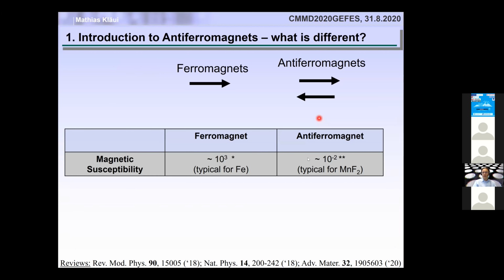Okay. Now we all know, because it's a magnetism session, that in an antiferromagnet, the susceptibility is much smaller, but it's not infinitely small. So it's like 3-5 orders of magnitude smaller than you have typically for a ferromagnet. And that just means that the antiferromagnetic sublattices are not very affected by applied magnetic fields.